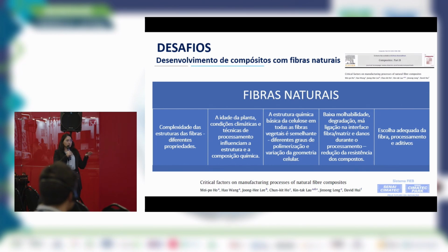The chemical structure is based in cellulose for all of the fibers. It's similar for the fibers. There are different degrees of polymerizing, and the grain size can play an influence on the fibers. They can have a low wettability, degradation during the process. So we should be concerned about the processing temperature for the composites. And then the interface, poor interface. So we must use compatibility agents during the processing when this happens. And all of the factors can reduce the strength. If there is no good interaction between the filler and the matrix, we may reduce the strength of the composites. So we need to properly choose the fiber, the processing conditions, and the additives that will be used in the product.